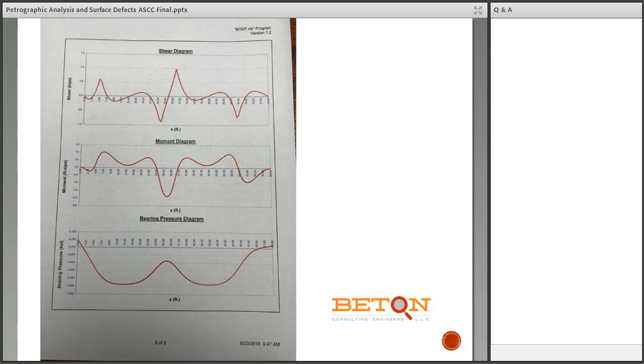So the petrographer, because the context is only the core, says, oh, early age cracking, that must be shrinkage. But in actual fact, a complete analysis, including some engineering analysis, shows that you cannot tell that, or in fact, in this case, determine that it is a design error and not a construction defect at all.